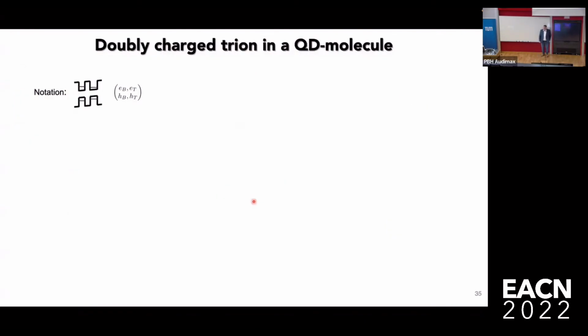Very important for what we want to do with the quantum repeater is the doubly charged trion. And this is a bit complicated, but I just want to show you quickly what you'll expect because we've actually seen this now. So this is my notation. If you see a matrix like this, this is how many electrons are in the bottom quantum dot, how many electrons are in the top quantum dot, how many holes are in the bottom and the top quantum dots. So if you place 2 electrons in such a system, so a doubly charged quantum dot molecule, these are the different basis states that you can create. And you see I've indexed their spin there. So you can either have singlet states, where both of the electrons can occupy 1 orbital in one of the 2 dots, or you can have triplet states, or you can have a singlet state where both of the electrons are in the other dot.